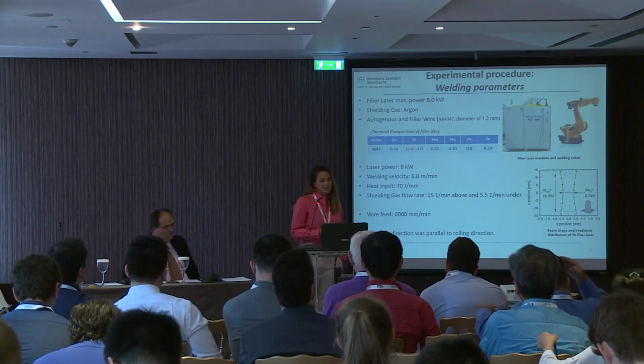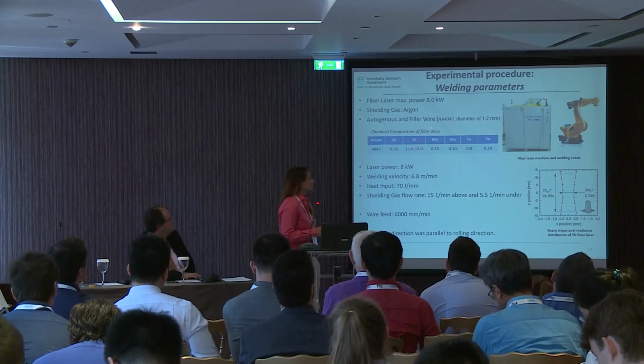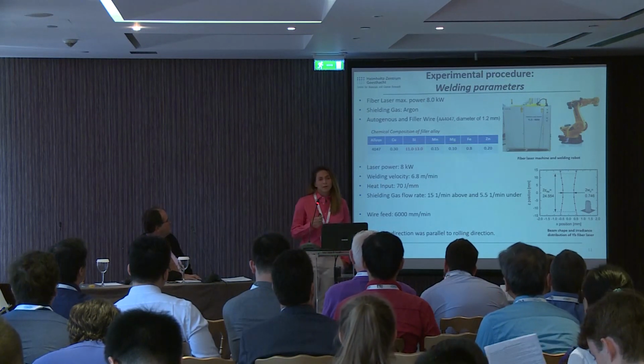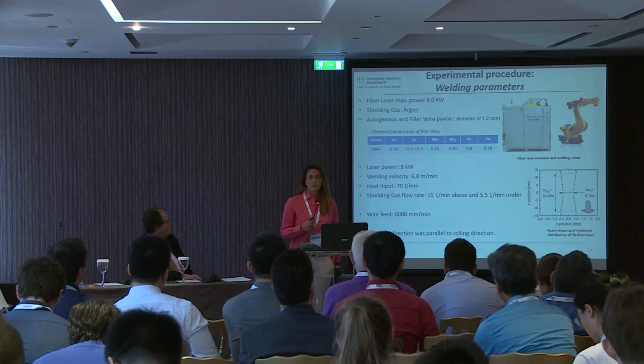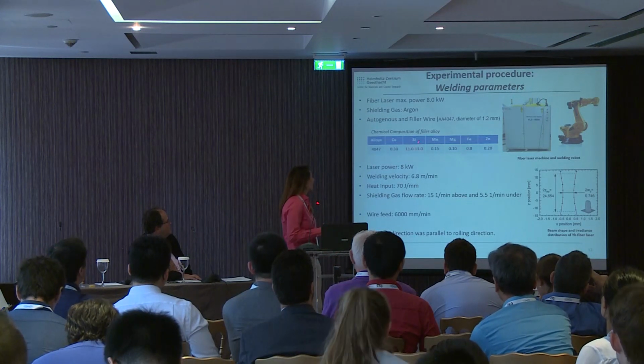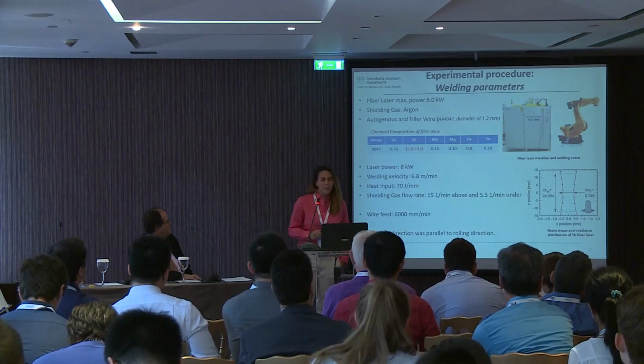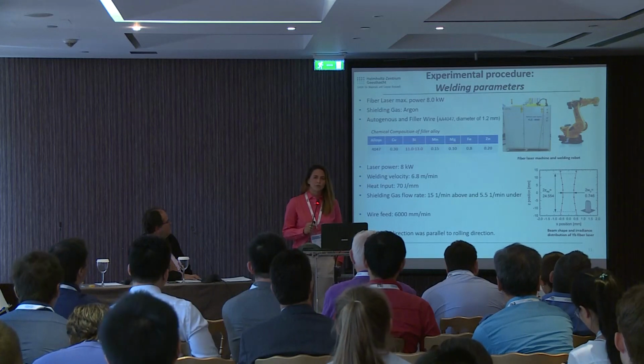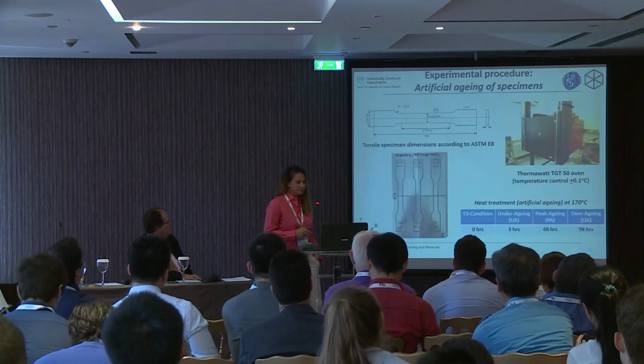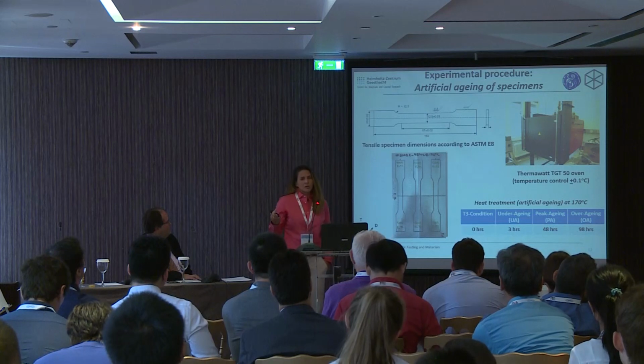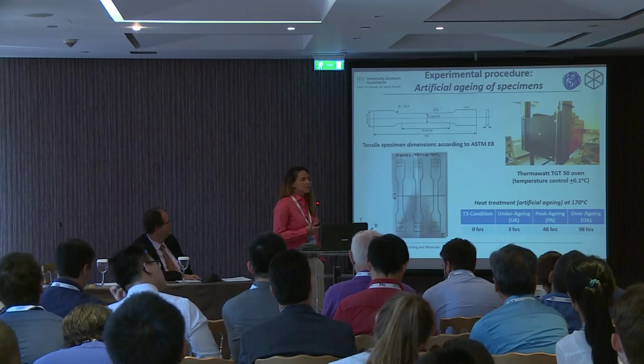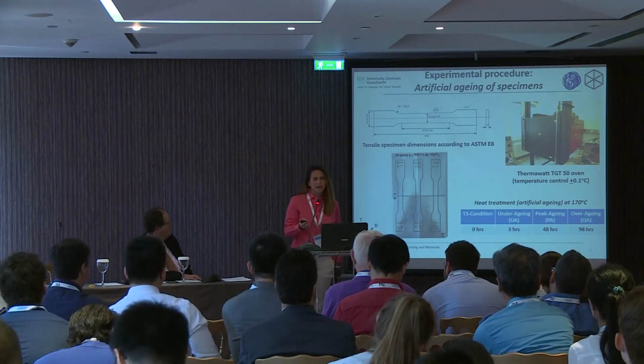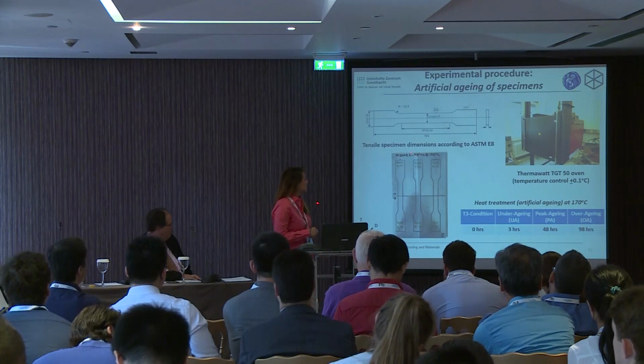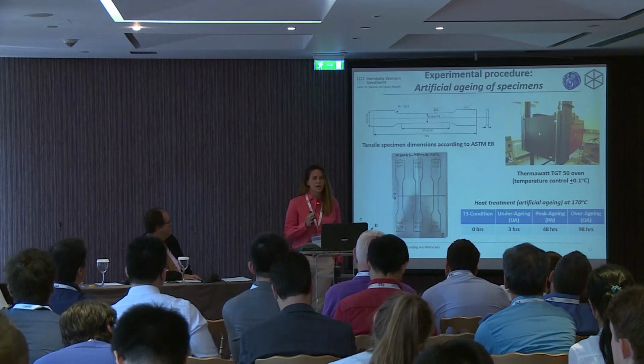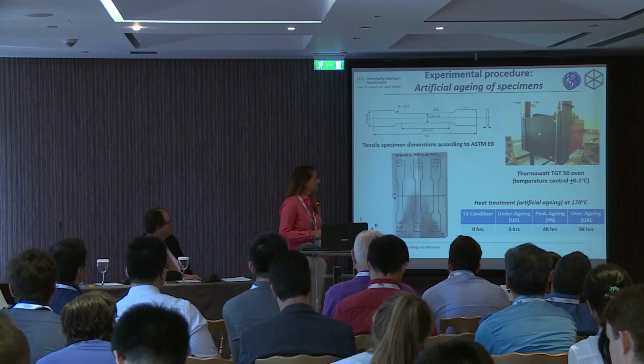and we used argon as shielding gas. As I said, we had autogenous and filler wire. The filler wire material that we used was aluminum alloy 4047, which is a silicon alloy, with 1.2 millimeters diameter. In all specimens, the weld was in the center of the gauge length. Here you can see the tensile dimensions according to the ASTM specification.